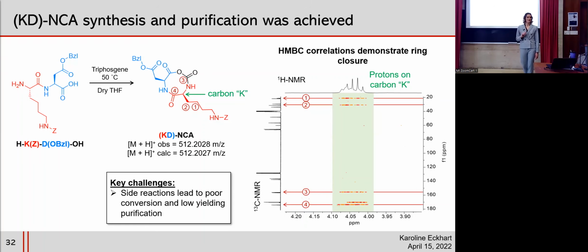Unfortunately, there were still some complications with this. The main one was that we were getting some side reactions in this reaction that probably led to, or were the reason behind, poor conversion. We only reached about 60% conversion after 5 hours, and that plateaued. And because of these side reactions and the poor conversion, the purification strategy was very difficult. We were able to purify this, but the yield was only about 12%, which I see as kind of a loss, but Stephanie always reminds me that 12% yield for a macrocyclic peptide is actually really good. So I want to be better though. So that's a future direction.